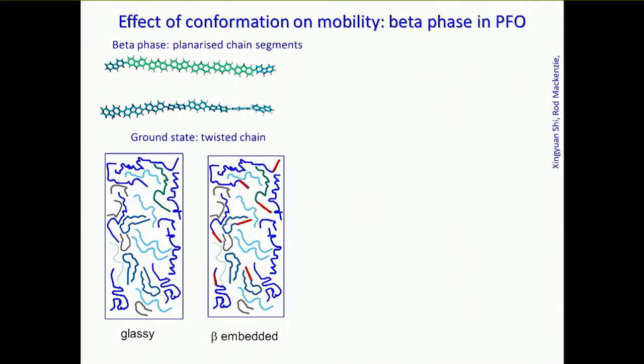And the choice of the polymer is important, because in the case of poly(9,9-dioctylfluorene) (PFO), the polymer is capable of forming not only its natural kind of conformation, where you have a twist of about 40 degrees between the consecutive segments in the chain, but it's also capable of forming segments where you have quite a significant number, maybe something like 10 or more monomers, which are lying in a metastable coplanar configuration. So they're completely flat. It's not the minimum energy structure, but it can occur, and it can be induced to occur. And we call this a beta phase.